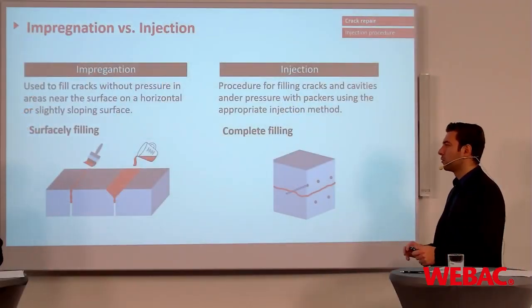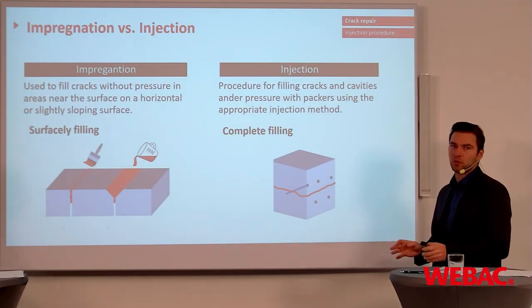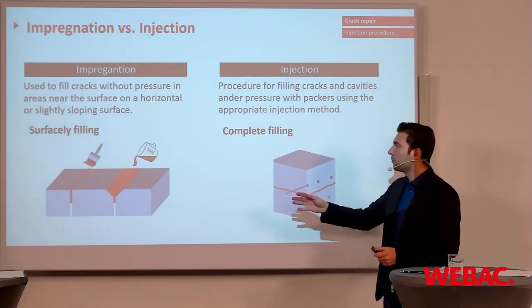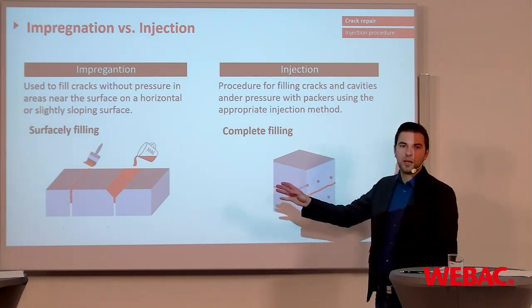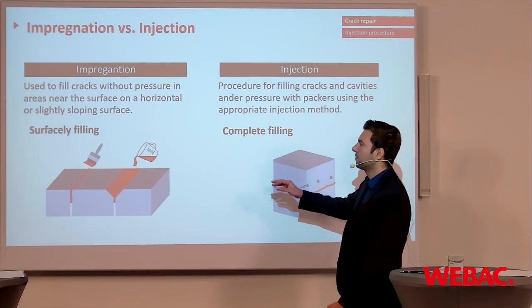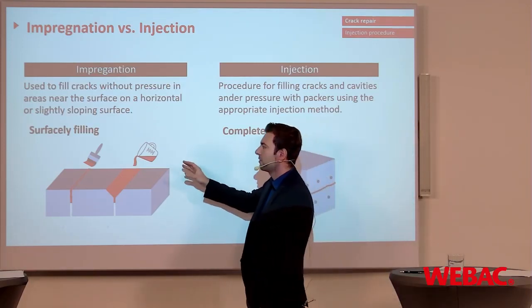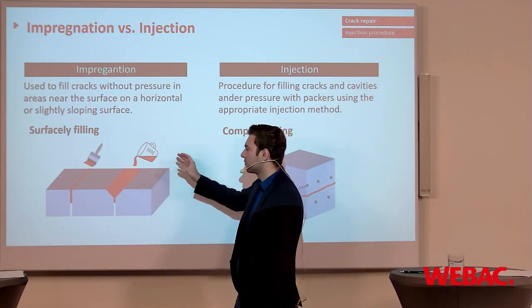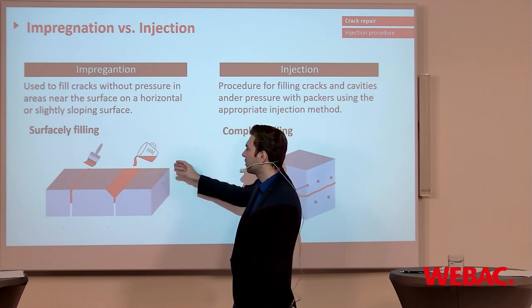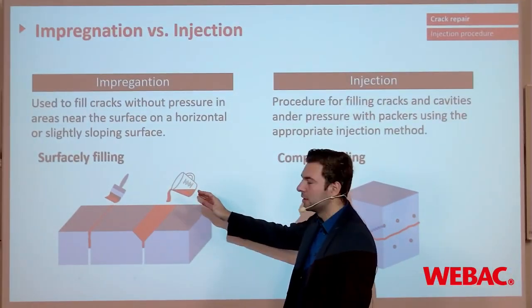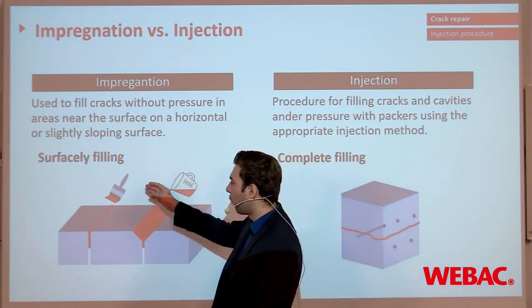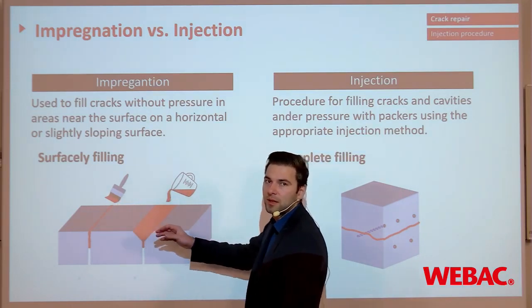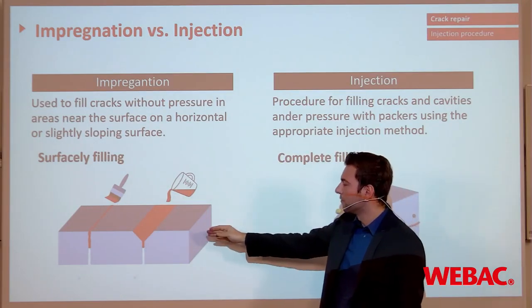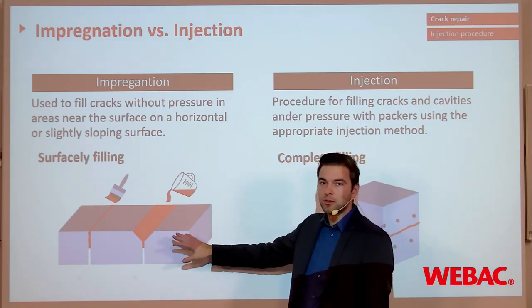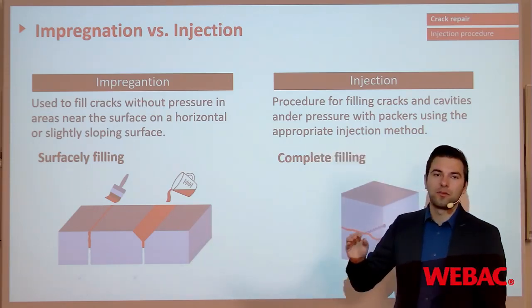So usually there are two ways to seal cracks in concrete. First of all, we are talking about impregnation, which goes into the structure by gravity. You just pour the injection material into the crack, or you brush it in. As you can see, the filling grade is not that good, and therefore it's only a surface filling.